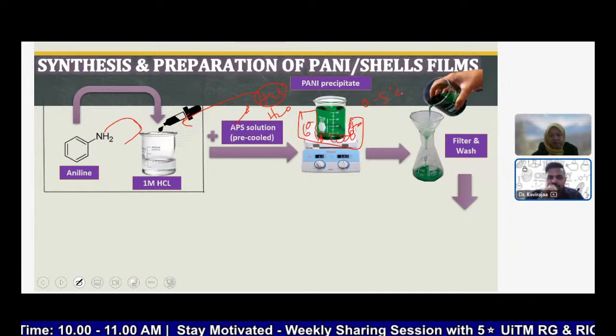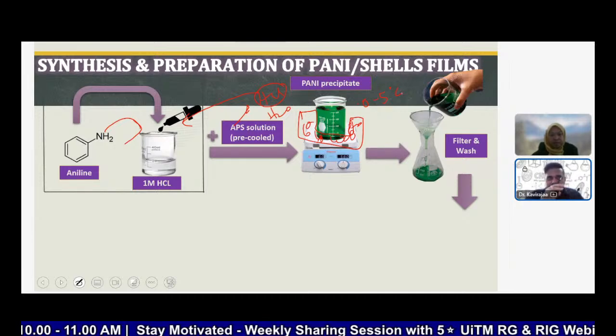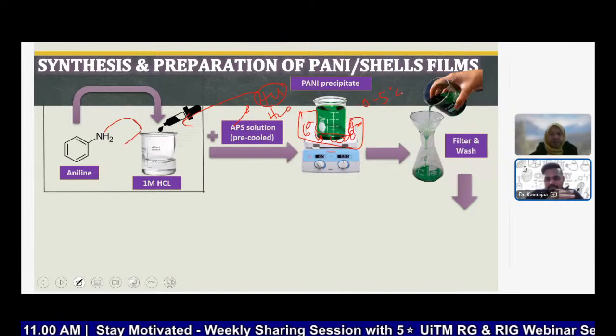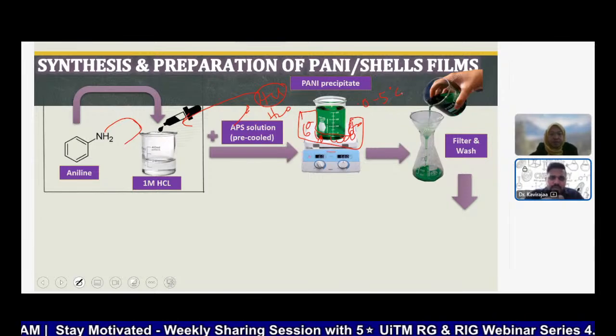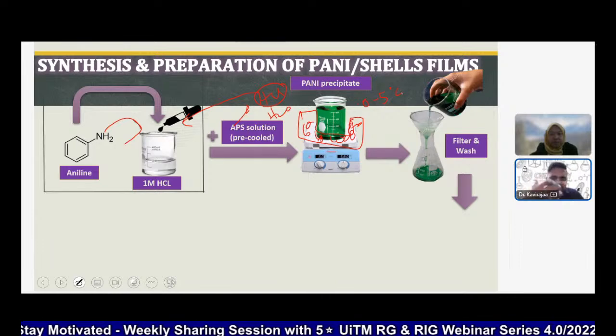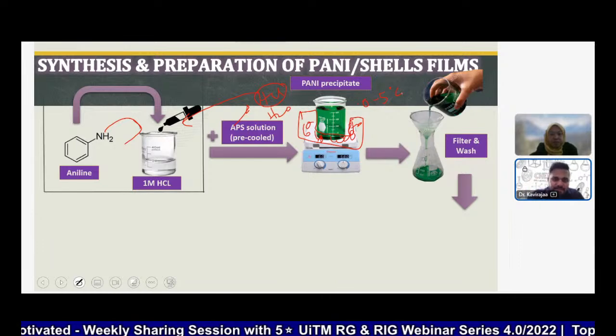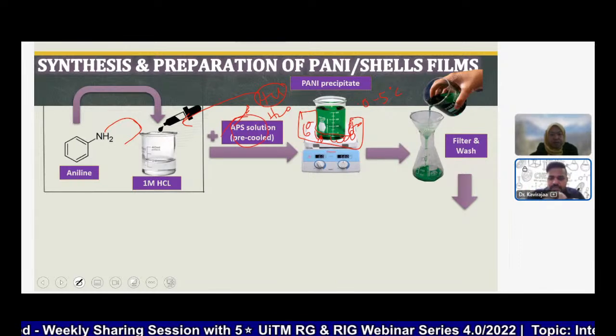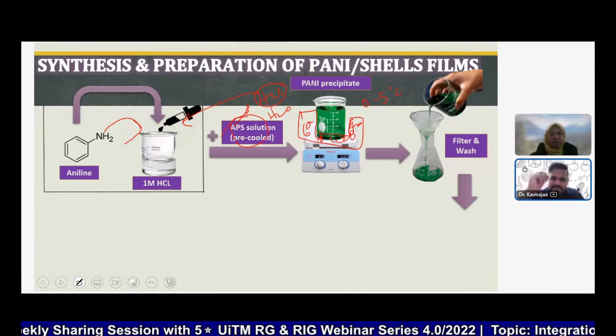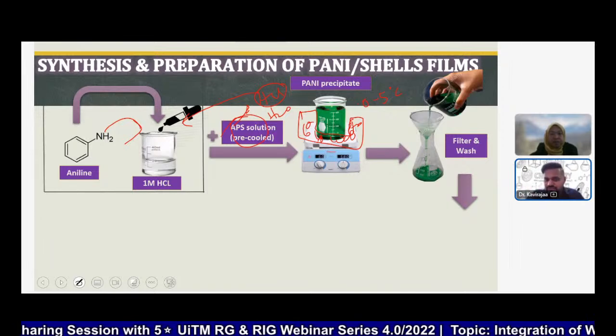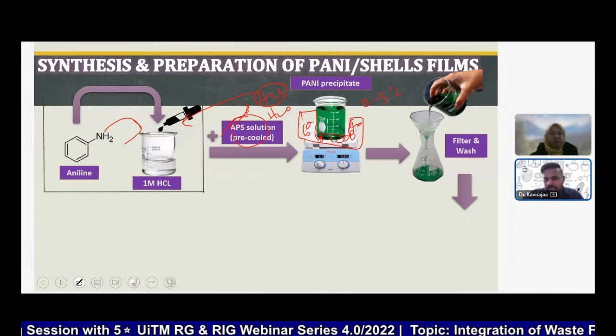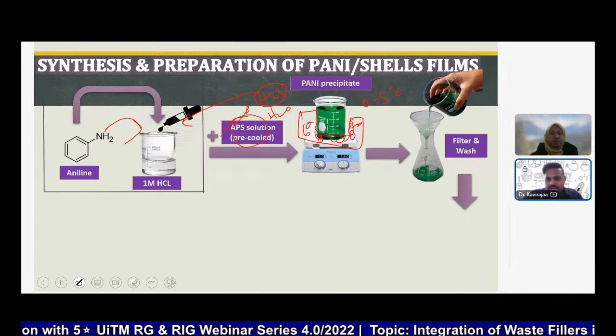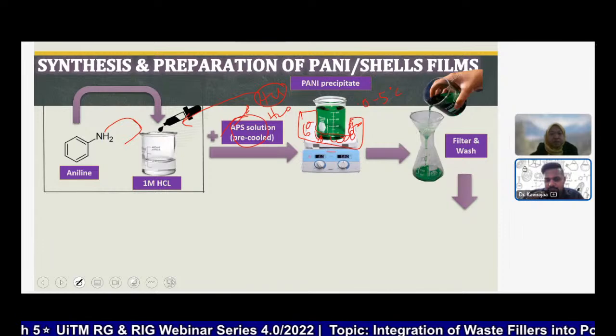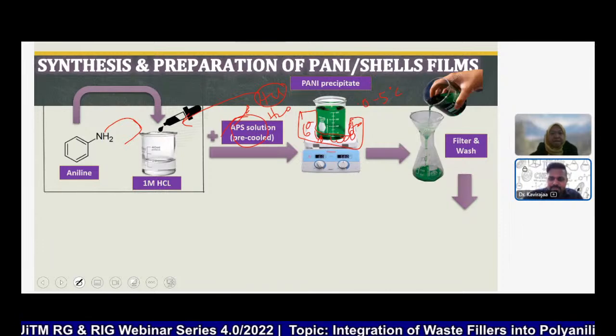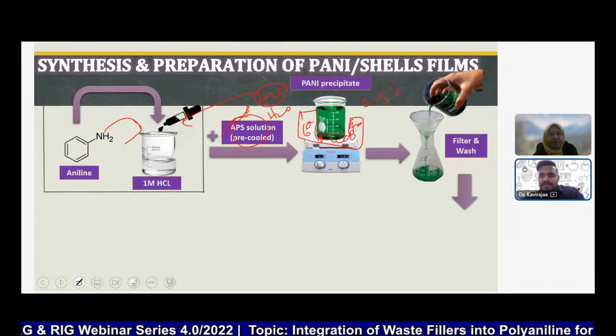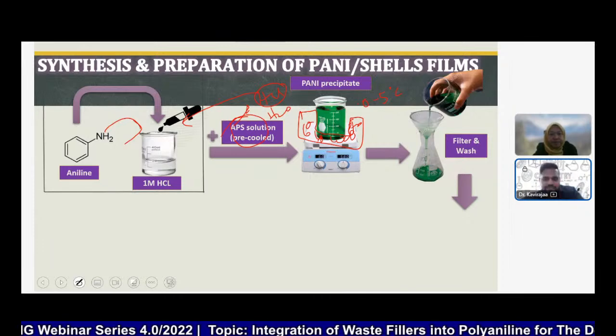Okay, the constant here is that almost any polymerization is an exothermic polymerization. Exothermic means it's going to release heat. On top of that, when APS, the oxidant, is added, it will release additional heat energy as well. For this conducting polymer, polyaniline, heat is typically not preferred because during my PhD, I did a comparison between room temperature and also 0 degrees Celsius.